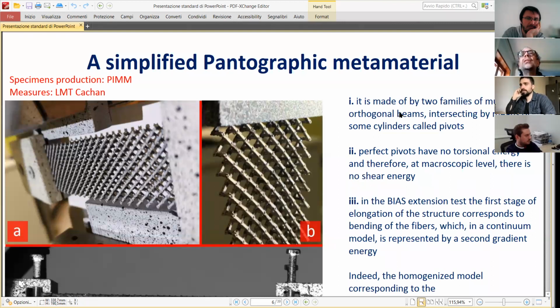Are these dreams only dreams, or can they be transformed into real life objects? Okay, we printed this structure. As you see, we tried to get quasi-perfect pivots in this specimen. And this material is made of two families of mutually orthogonal beams in the reference configuration. They are intersecting by means of some cylinders, which we call pivots. Perfect pivots have no torsional energy, so there is no macroscopic shear energy when you deform this sheet.